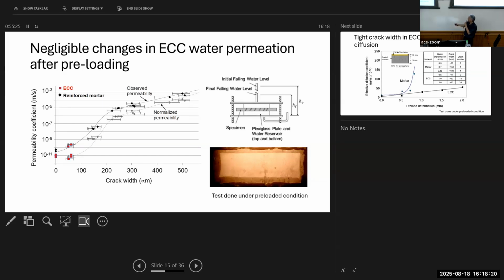Now, for the other data, some of it comes from our lab and others from other people's labs. I believe a lot of the data came from Professor Surendra Shah's lab, where they did permeability testing of concrete specimens that had been preloaded to different crack widths. And you can see that these curves show a very rapid rise in permeability. This is not a linear chart. This is a log chart here. So every step here is increasing by hundreds, okay? So from 10 to the minus 11 going to 10 to the minus 5 is 6 orders, 1 million times higher when you increase the crack width from, let's say, 100 to about 400, 500 microns, okay? So that is very, very fast penetration.